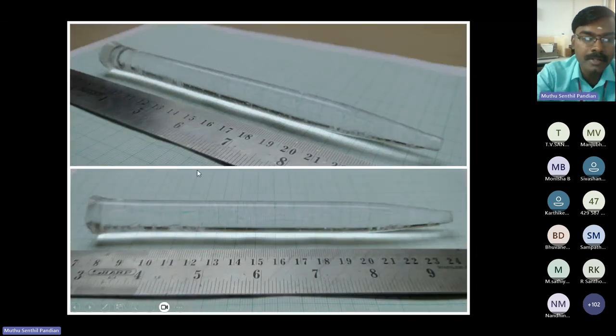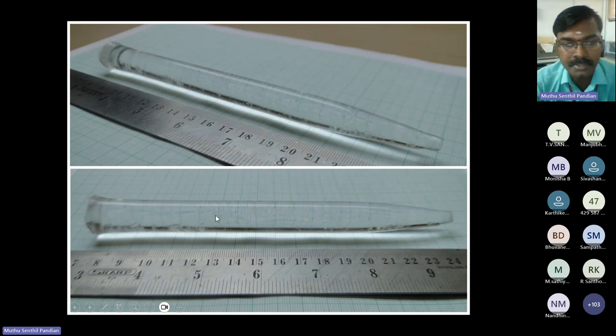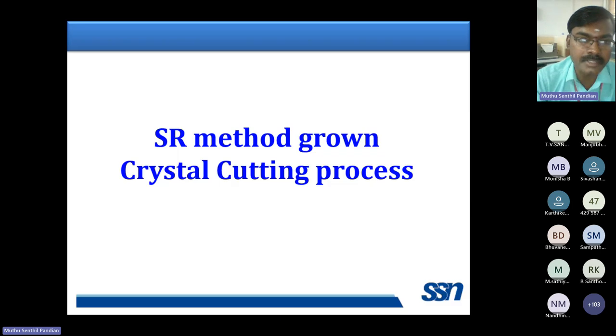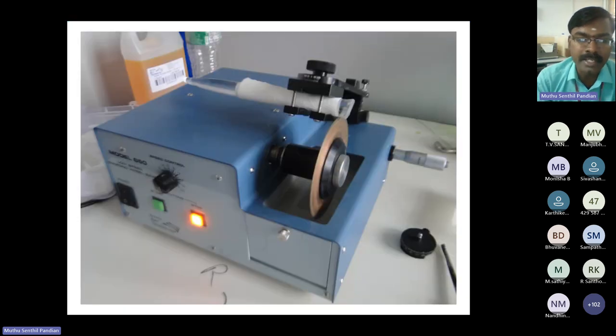You see, there are no microcracks or milky opaque regions in the SR method grown crystal, because we have maintained uniform temperature, stable supersaturation and uniform growth rate. So there is no chance of the formation of all these defect structures in the SR method grown crystal. Now, how to cut the crystal for any application or characterization?